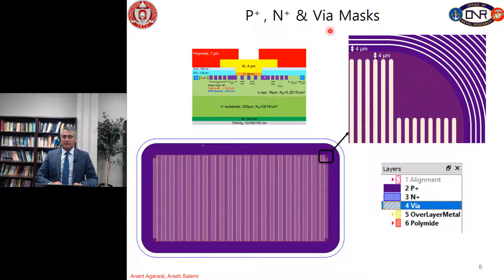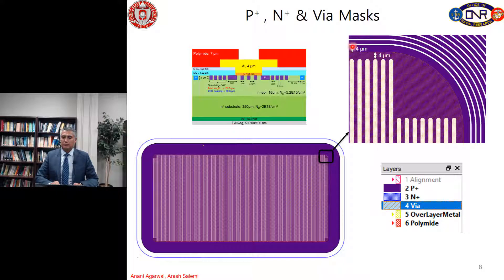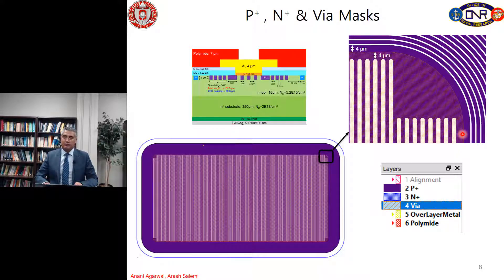The next mask is the via mask, used to etch the silicon dioxide and silicon nitride and reach the surface of silicon carbide, then deposit titanium and so on. For this mask we need an overlap of 4 micrometers over the via in order to be sure that the titanium can deposit on all parts of the fingers. This overlap distance is very important for all power device designs, so be careful about these overlayers every time you are designing a mask.